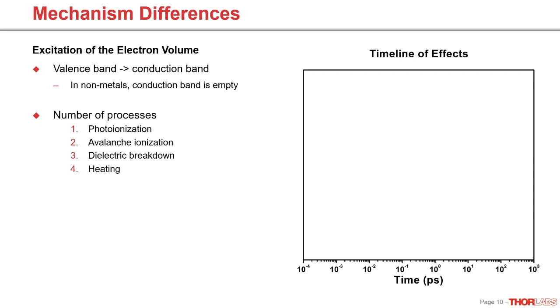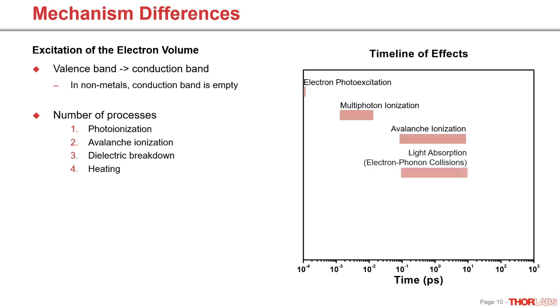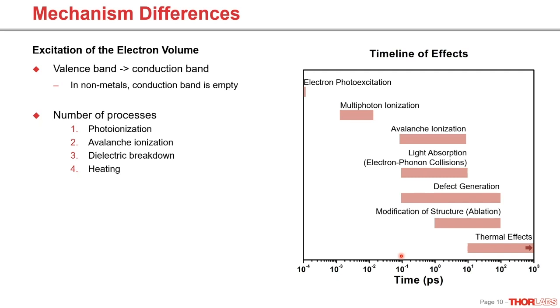So first, I want to play this brief animation for you, which is kind of a timeline of effects of what happens as a laser pulse impinges upon a material. And essentially immediately, approximately a femtosecond, we're getting electron photo excitation. And then we get some of these other processes occurring, and I'm going to get into them in a second. So basically, when a laser impinges upon a component, you get some excitation of the electron volume. And in nonmetals, the conduction band is empty. And what we're going to do is drive the electrons from the valence band to the conduction band. And that is going to result in some of these effects happening, because we're going to start seeing some localized absorption. So, we're going to see photoionization. Then we're going to see avalanche ionization, followed by dielectric breakdown, and then that's going to be followed by heating.